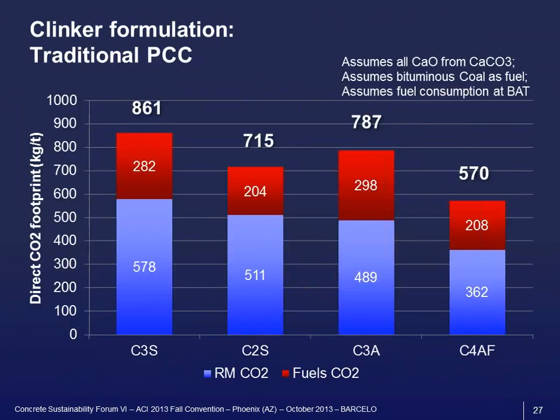So here I have calculated the CO2 footprint for the different phases of Portland cement. So this is in kilogram of CO2 per ton of phase. You have C3S, C2S, C3A, and C4AF. The blue portion is the CO2 coming from the decarbonation, and the red portion is the CO2 coming from the fuels. And this is calculated assuming a very modern plant, 5 stages preheater with precalciner. What you can see is that really the C3S and the C3A are the two phases that have the higher CO2 footprint.